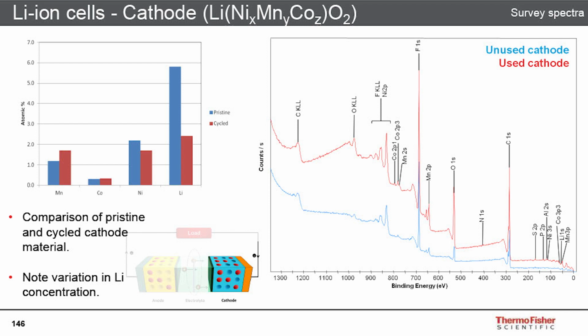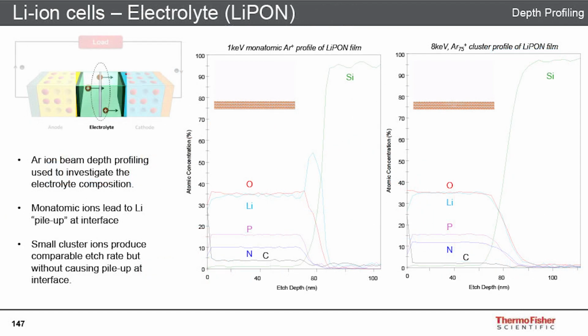And so looking at those SEI layers is one of the things that XPS is used for as well, quite commonly on these types of materials. For the LiPon material in the electrolyte area, we were looking at a depth profile here to see how consistent the material was. And we tried doing it with a monatomic argon profile, and we found this increase in the lithium signal here at the surface when we got to the silicon.